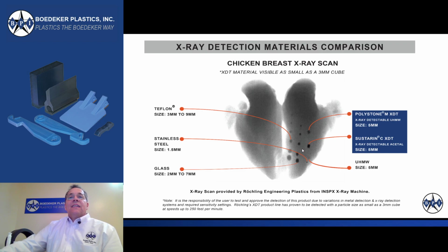And again, the glass appears very clearly and is certainly detectable by the X-ray. The next row here are actually pieces of Teflon. Again, pieces of PTFE ranging from 3 millimeters to 9 millimeters in size. And again, you can see those quite clearly. But that is virgin Teflon, that has no metal or X-ray detectable additives in it.